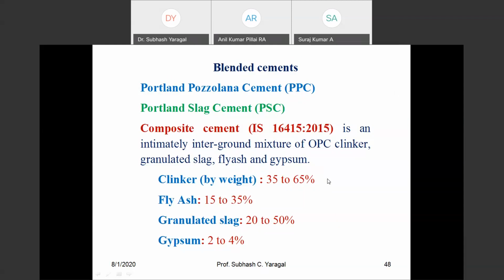Now I'd like to draw your attention to the composite cement, which has been recommended by the Bureau of Indian Standards. It is an intimately interground mixture of your OPC clinker along with slag, along with fly ash. Now, you are going to use your OPC clinker to the extent of either the lower limit or the upper limit. So you still preserve around 35% of your deposits. But use fly ash 15 to 35%. Use your ground granulated slag 20 to 50%.